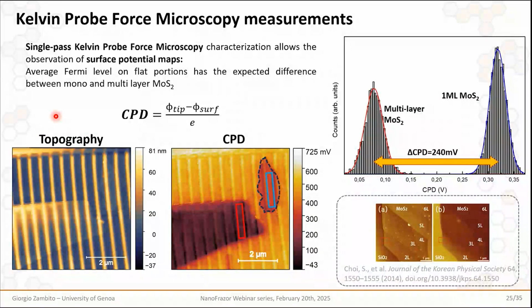Kelvin probe force microscopy is an AFM-based technique, which is performed in tapping condition and which exploits conductive probes to measure the so-called CPD, the contact potential difference. And this is actually related to the work function of the surface. The work function of the surface is related to the CPD signal in this way: basically, it's represented by the difference between the work function of the tip and the work function of the surface, normalized to the unit charge.